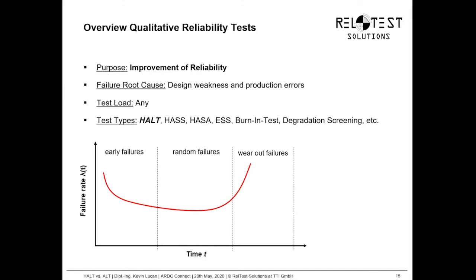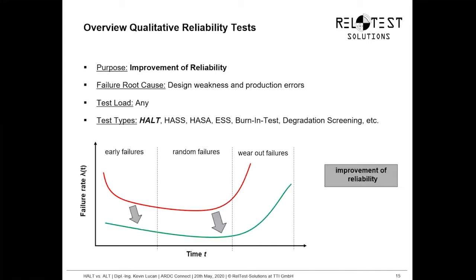Let's have a look at this in an example of the bathtub curve. Let's assume we have this kind of product. We haven't measured it, but if we had measured our failure rate, this would be the result. When we are doing highly accelerated life tests, we are identifying our design weakness. If we are doing HASS, ESS, or burn-in tests, we are reducing production errors. This helps us to shift the bathtub curve down, to reduce especially the early failures and to improve the reliability. Therefore, the main focus of qualitative tests is the early failures. So we want to improve the reliability and fix these kinds of failures.